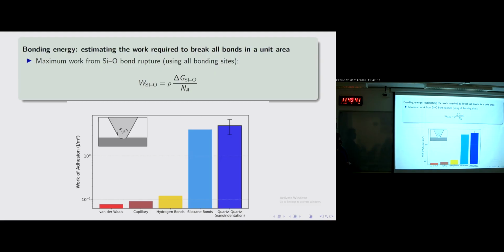Chemists are really useful, and they know the change in Gibbs free energy for rupturing or forming different bonds. So for a silicon-oxygen bond, that's about 450 to 500 kilojoules per mole. And this is just Avogadro's number. And when I do this calculation and compare it to the work of adhesion that I get from my experiments, I see that they're kind of close together.